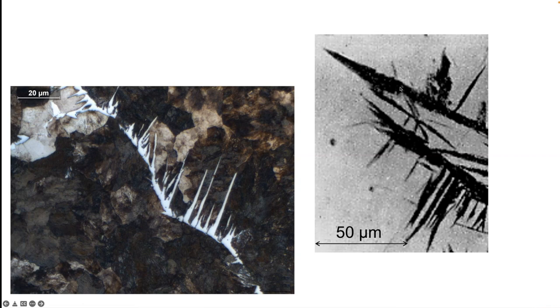And I explained to you that the bainite etches dark because there is fine structure inside what appears to be a single plate, which is actually thousands of small platelets with intervening phases such as carbides or austenite. Here, this is completely clean, okay? So there is no structure inside the plate of Widmanstätten ferrite. It etches white, just like the ferrite which forms at high temperatures.